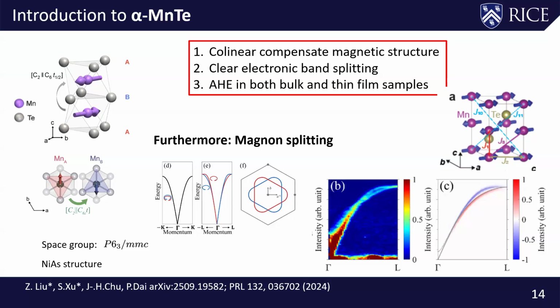Something on the previous slide. Is there something anomalous about this hysteresis loop? Yes. Or is it just that there's no order? The reason it's actually interesting is mostly the fact that you have this hysteresis loop, and in a strictly long-range ordered antiferromagnet, there shouldn't be any net magnetization. And the system does have an extremely small net magnetization. People think it might be a small canting, or it's not completely clear. But yet you have this hysteresis loop for a magnetic field applied along the c-axis. The hysteresis itself is normal, except for the fact that the moment is exceedingly small. Strictly speaking, in a completely collinear antiferromagnet, it shouldn't be there.